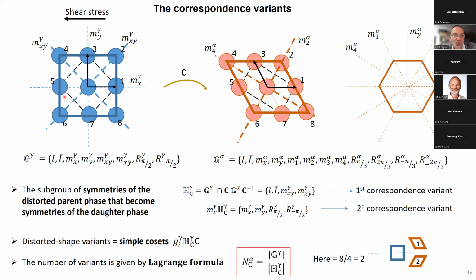If you look at this diagonal mirror symmetry here, it establishes a mirror symmetry between atoms 3 and 1 here. And after the distortion, we still preserve this symmetry. Atom 3 is still in mirror position with atom 1. Okay, these two mirror planes are not parallel, but we do not care. What is important is the relative position of the atoms to each other. So we adopt the same approach, but instead of taking into account T, the orientation matrix, we take into account C, the correspondence matrix.